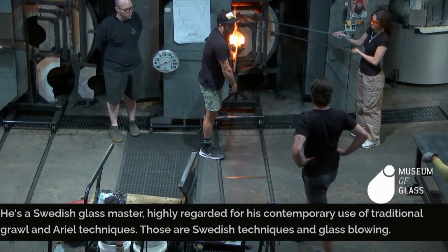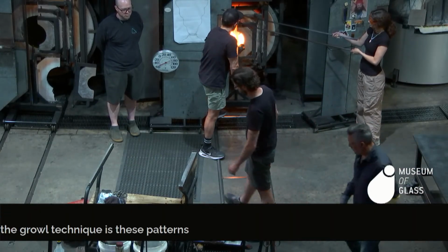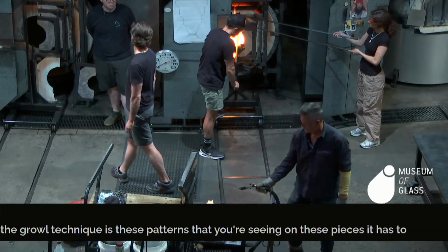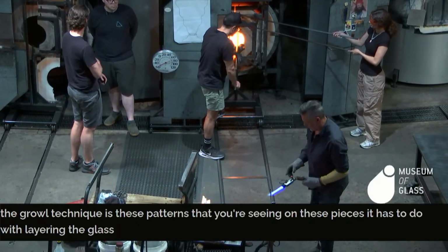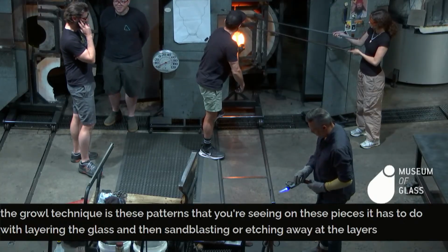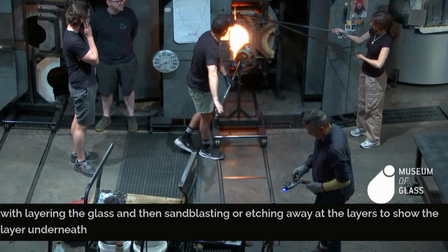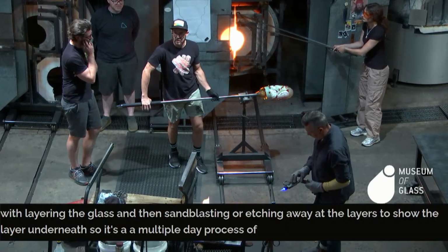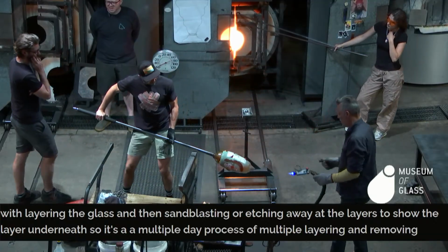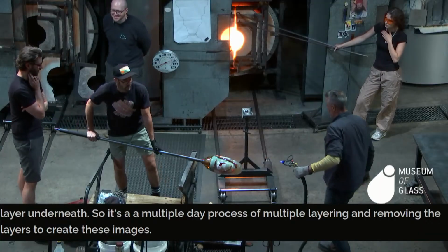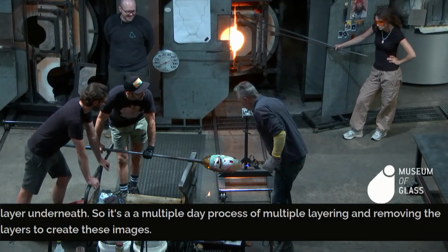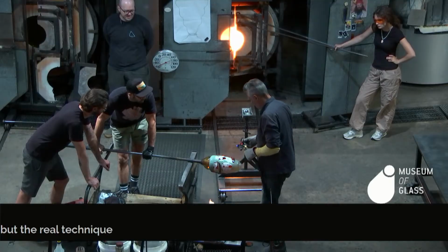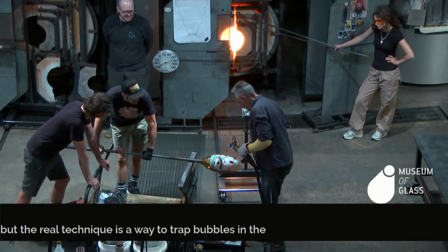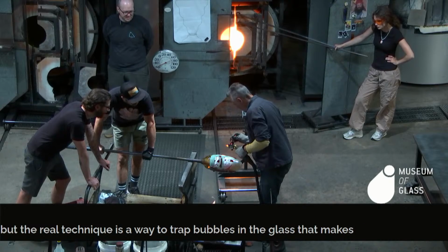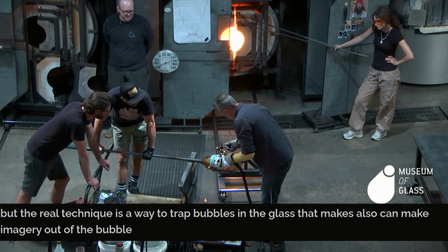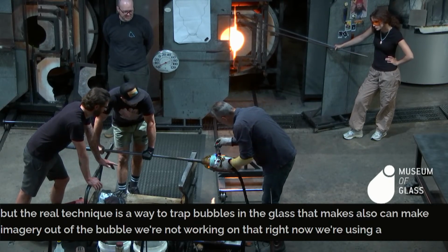The Graal technique is these patterns that you're seeing on these pieces. It has to do with layering the glass and then sandblasting or etching away at the layers to show the layer underneath. So it's a multiple day process of multiple layering and removing the layers to create these images. But the Ariel technique is a way to trap bubbles in the glass that also can make imagery out of the bubble. We're not working on that right now. We're using a Graal today.